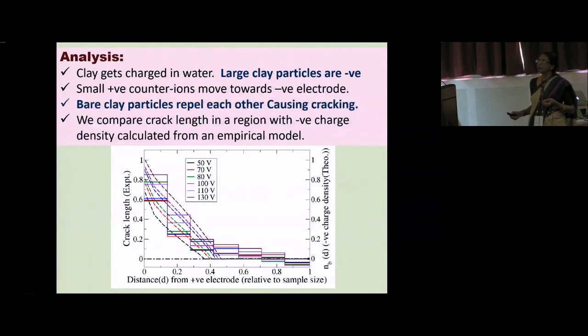And we also did a very simple calculation based on this model. I'm not going into the details of the model here, but these broken lines are what we got from the calculation, and you can see that if we compare with our experimental steps, then this is more or less in agreement. After some point, the number of cracks or crack length does not decrease any further. It goes right up to the other end. As we noticed, the tree trunk at some point stopped, there is only one. So finally, we have only this number of cracks which reach the other end.